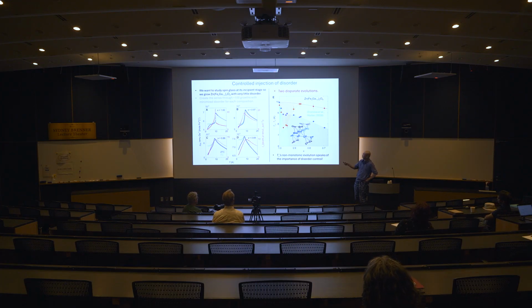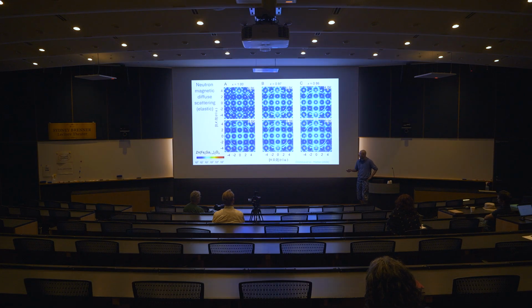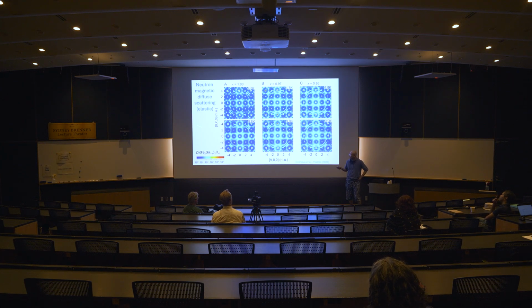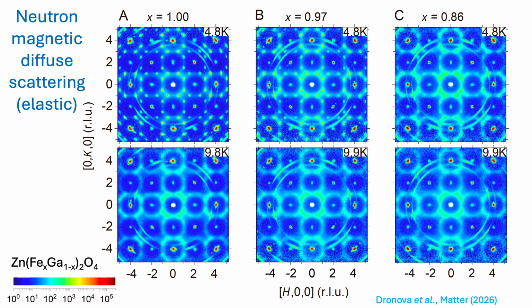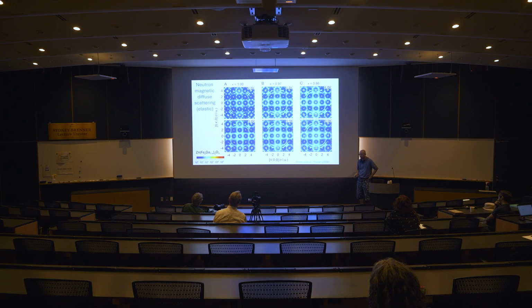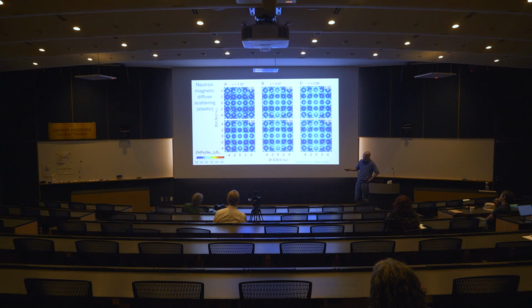With that, we take three samples: one at the purest condition, one at 97%, one at 86%. We take these three extreme cases to the neutron experiment. What you can see is that at high temperature, 10 Kelvin for example, all three samples have exactly the same behavior: diffusive, no Bragg peak, and very consistent patterns. However, if you cool down to half the temperature, 5 Kelvin, the disordered sample still remains more or less the same. The pattern does not change across temperatures. However, in the pure sample, you can see this diffusive part becomes a single spot. And the 97% sample sits in between, but you have a very clear spot here.